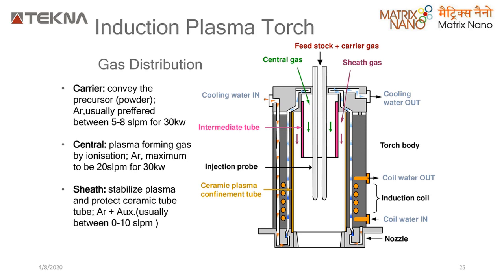So you have carrier gas, which is usually argon. That is what we prefer. Argon is a very inert, cost effective, industrially comfortably available gas. Also, you can use helium for R&D applications when you want to be more precise. So these are certain values, like how much is the pressure which we use, or what the flow rate of gases, say 5 to 8 liters per minute is what we use. Standard liters per minute of argon is what we use as a carrier with the powder.